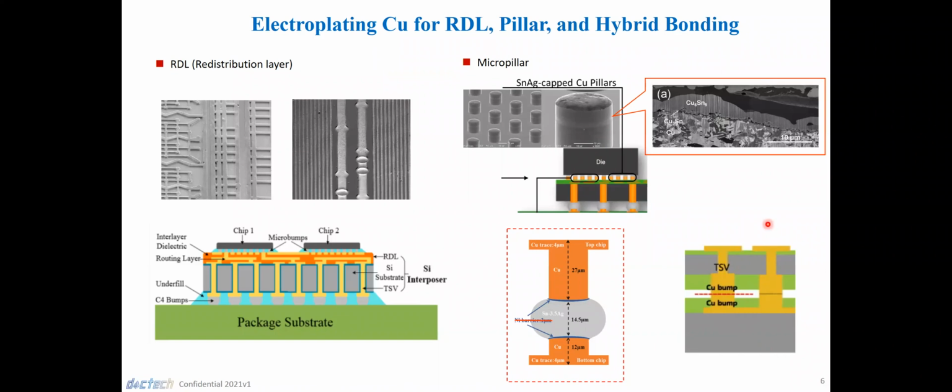In the future, copper to copper direct bonding appears to be the solution to the problem of Joule heating and electron migration, because it is a homogeneous interface, just copper and copper together. However, when the size becomes small, electron migration will still happen in copper to copper bonds when the current density is over 10 to the power of 6 amps per centimeter squared. Moreover, normal electroplated copper is soft and possibly cannot withstand the high bonding pressure for direct copper-copper bonding.